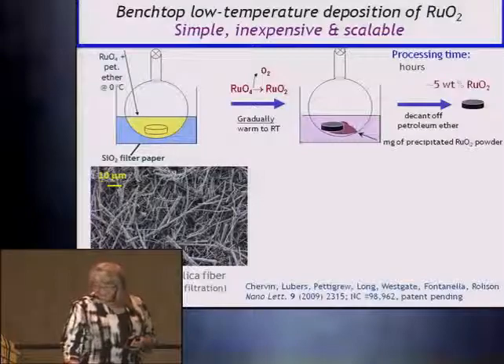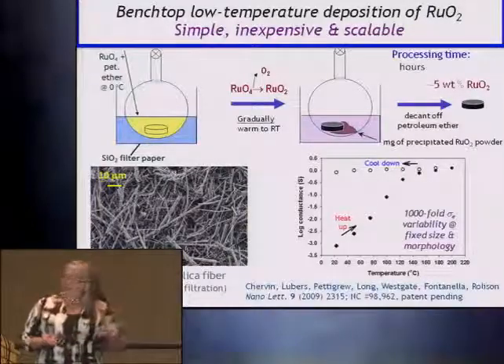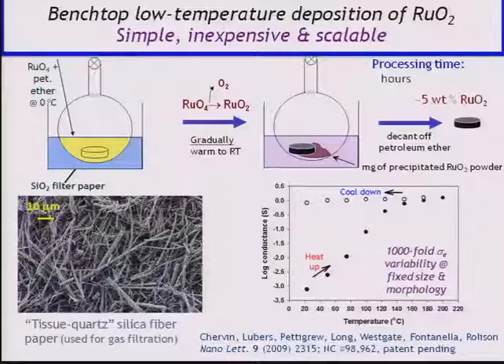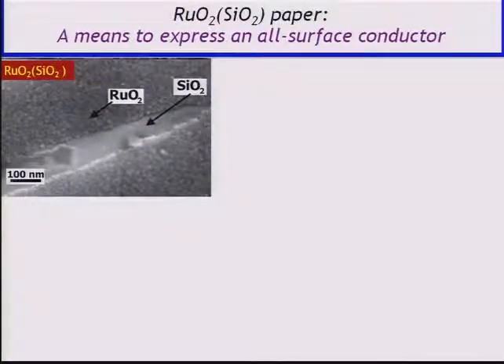What comes out is black, and it's conductive, but not greatly conductive, same thing we saw with the aerogel. But as you heat it in air, it just improves its conductivity up to 3 orders of magnitude, as long as you don't go much past 220. And wherever you cool down at, it retains whatever the conductivity was there. So now we have a sort of a nanometric form of RuO2 with 3 orders of magnitude delta in its conductivity, which of course the physicists love, because they can go in and ask all sorts of fundamental electron-phonon physics questions.